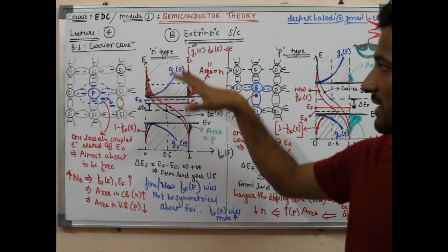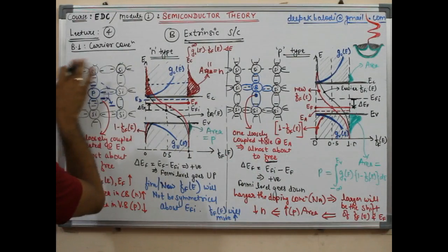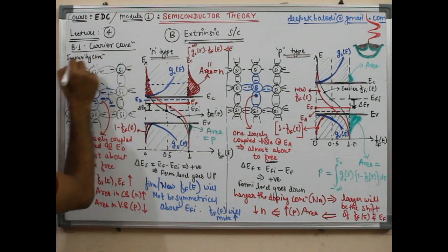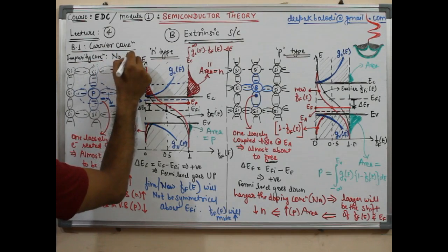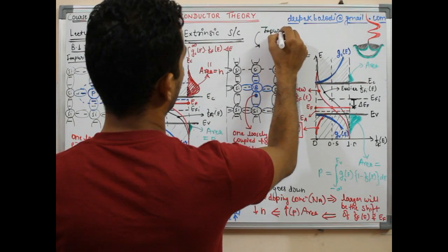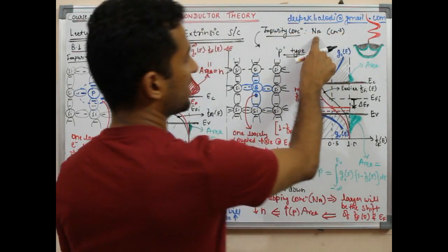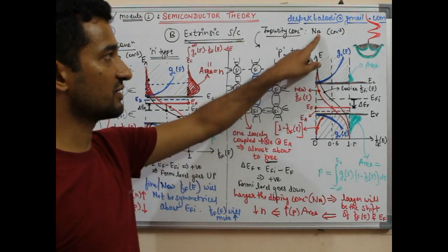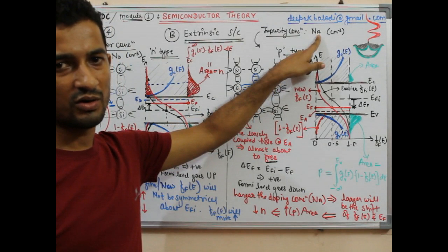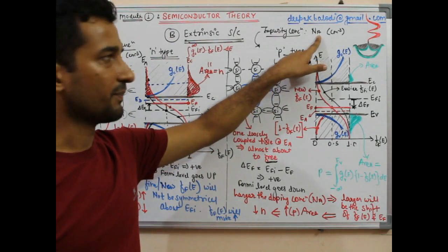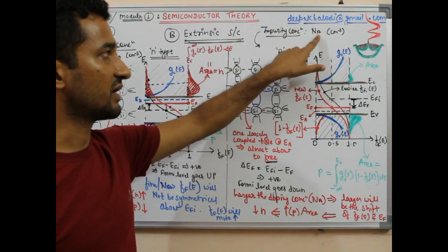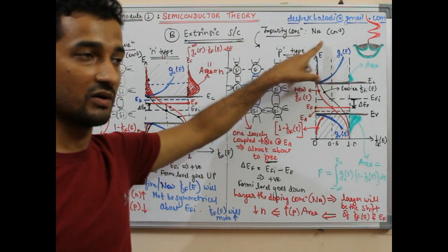So with n-type impurity, the impurity concentration I mentioned in the last, I'm sorry for that, but here I can say the impurity concentration, you know the example, phosphorus or arsenic, is Nd per centimeter cube, and here the impurity concentration is Na per centimeter cube. Like in the example of light doping, this Na is 10 to the power 11, 12 or 13 per centimeter cube. In case of moderate doping, this is 10 to the power 14, 15 or sometimes 16 per centimeter cube. For the case of heavy doping, it is 10 to the power 17 or 10 to the power 18 per centimeter cube. The same with this.